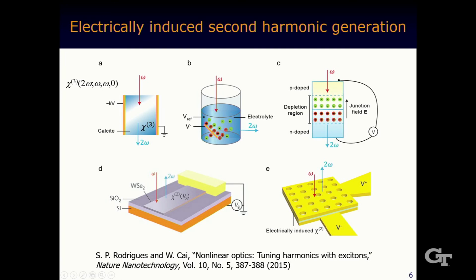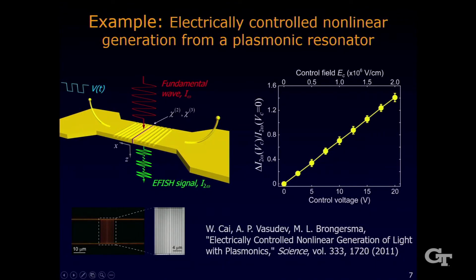Okay. And there are many different configurations we can use to generate this process, electrically induced harmonic generation. You can use a bulk crystal, an electrolyte or liquid environment, the depletion region of a p-n junction, some 2D crystals, and some nanoplasmonic systems. I have a review article focused on this. Let me show you the very first example, which is electrically controlled second-order nonlinear response from a single plasmonic cavity. This plasmonic cavity helps you condense light, and then you apply the voltage, and this controls the nonlinear behavior in a polymer, represented by this purple thing, which is fused within this nanocavity. As a result, there's very efficient tuning of the harmonic generation of light through this gap region by the applied voltage. This is pretty old research, about 10 years ago, I think.